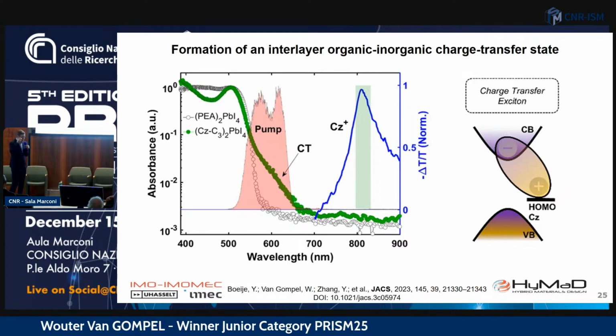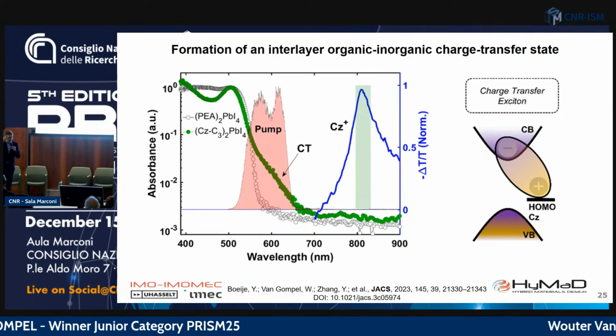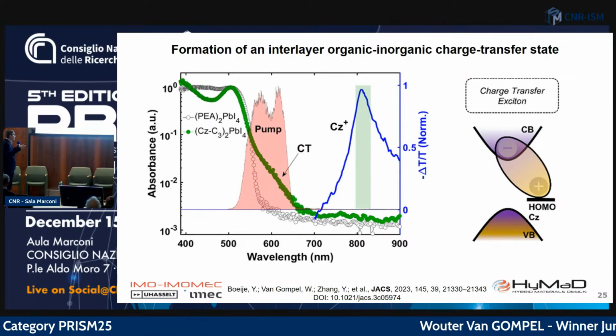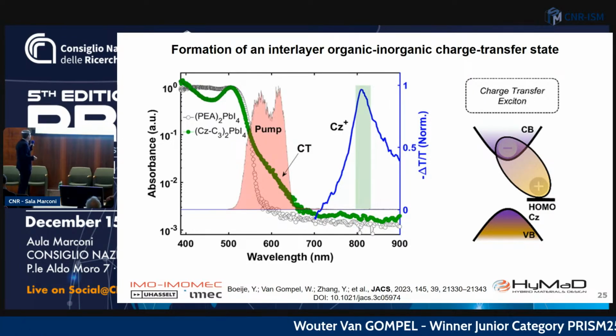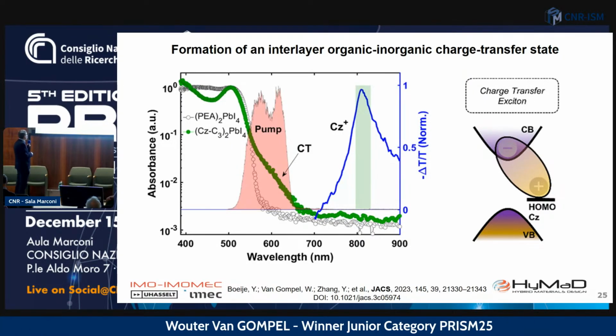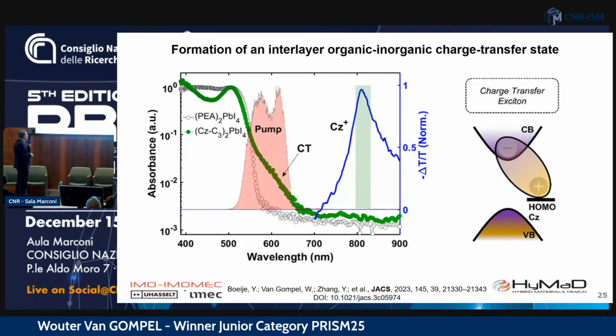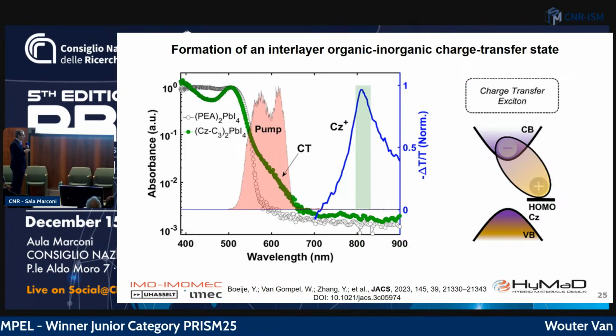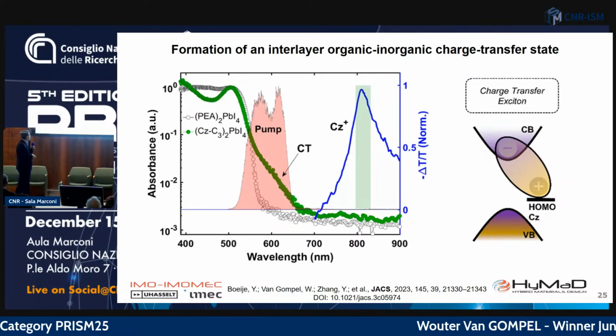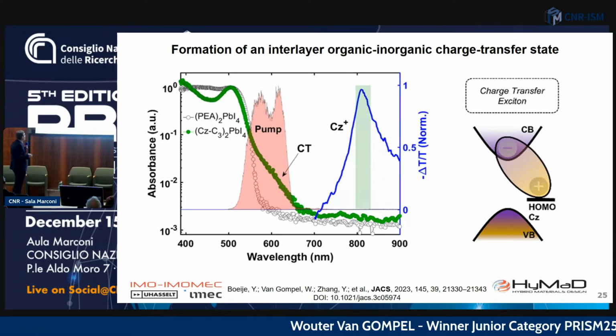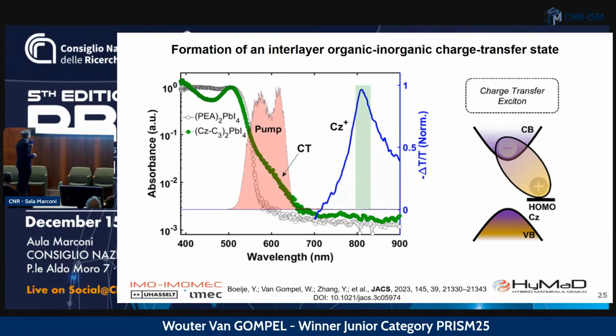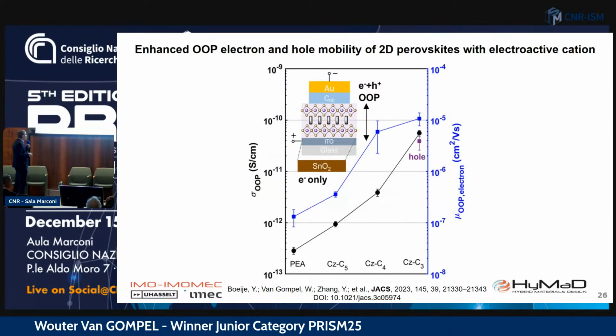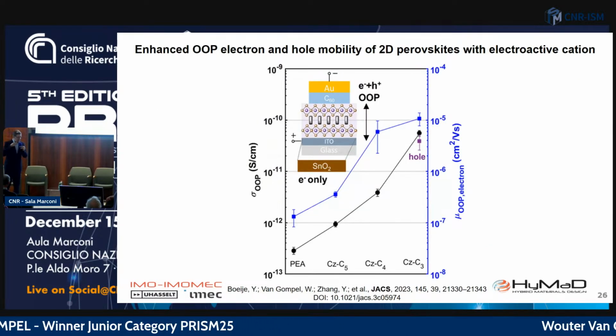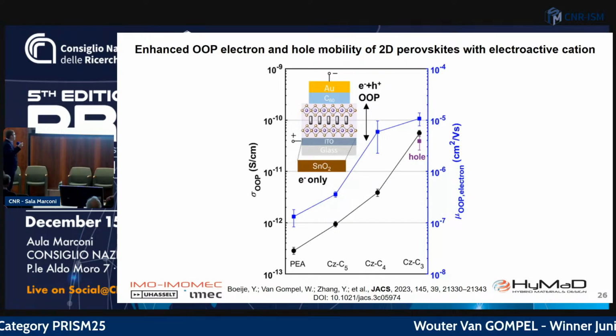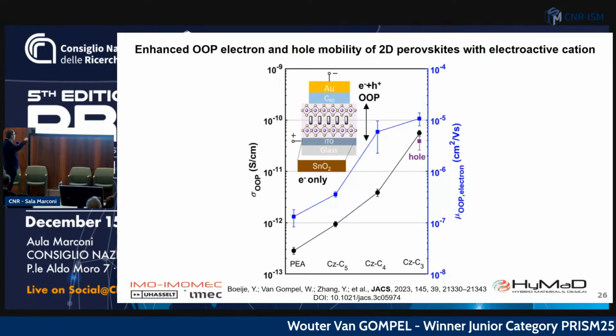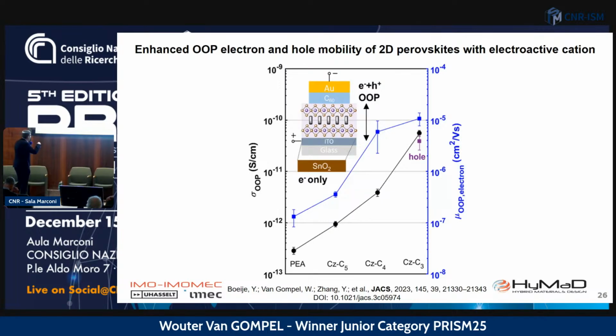Next to that, we also showed the presence of a charge transfer exciton, so really a combined state of the organic and the inorganic. In the absorption spectrum, you get a new CT band, and if you excite that one, you also get, again, carbazole cation radical photo-induced absorption. So some interesting combined organic-inorganic properties in this material. So why is it interesting? Well, one of the problems with the 2D in general is that you have a very low electron and hole mobility out of plane, because the organic acts as a barrier.